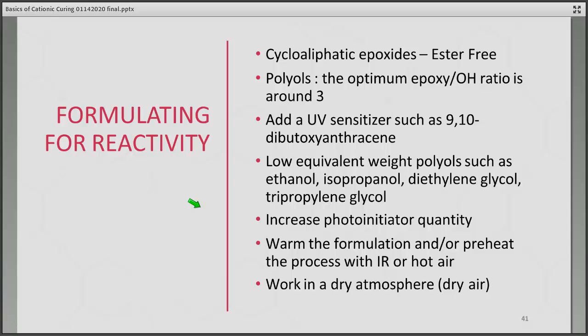You can warm the formulation or preheat the process with either IR radiation or hot air. Remember back when we talked about the mechanism of a UV curable cationic system, I mentioned that after the UV energy kicks it off, it then becomes more of a thermal process. So that's why, by adding heat to your system, warming it, you'll be able to accelerate that curing process. Also work in a dry atmosphere, as dry air will sometimes speed that up.